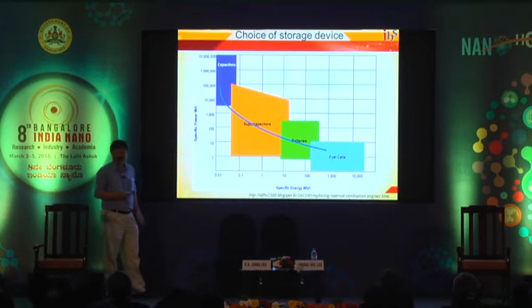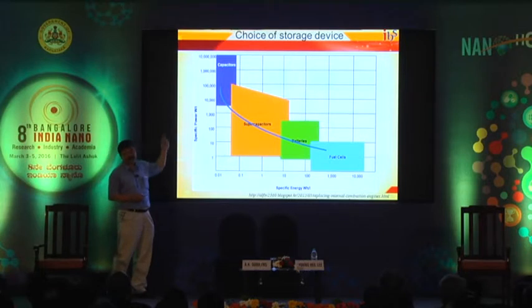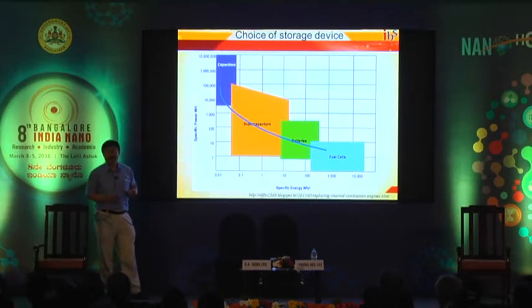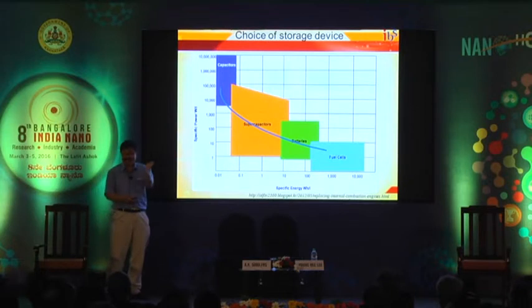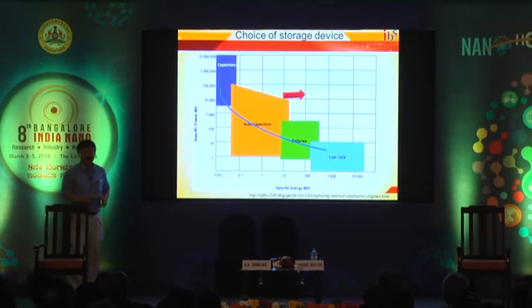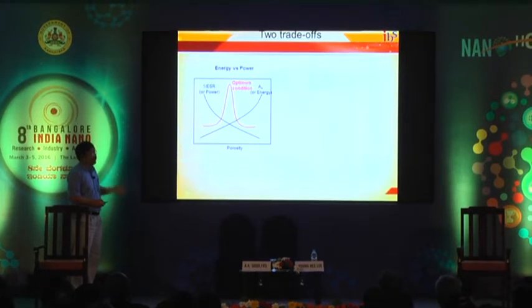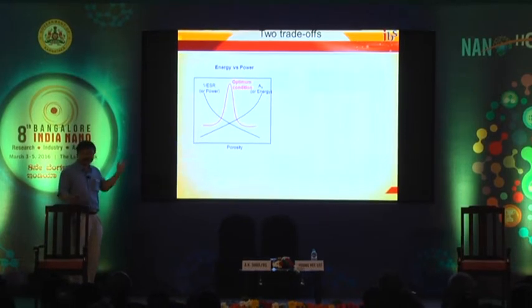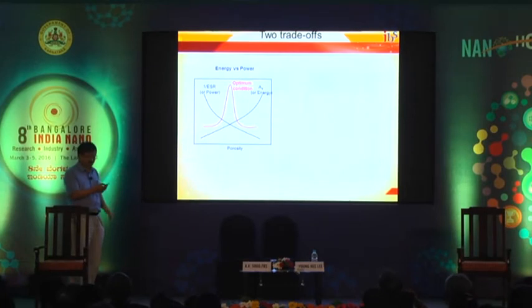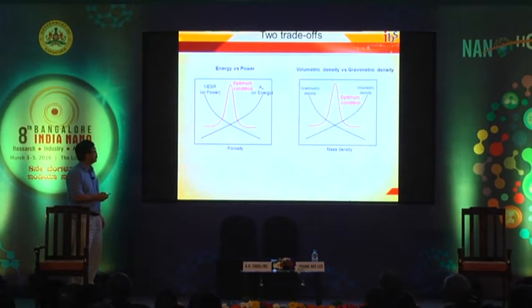Many people are working on different research directions. My choice is this capacitor because I believe that we have more freedom. Because the battery, for the last 50 years, has increased the energy density only by a factor of 2. So they are already saturated, because of mostly the cathode material. But when you work with this material, there is always a trade-off phenomenon. When you try to increase the porosity, energy density is good, but the power density becomes poor, things like this. So it's always mixed up. So you have to really play hard on this.